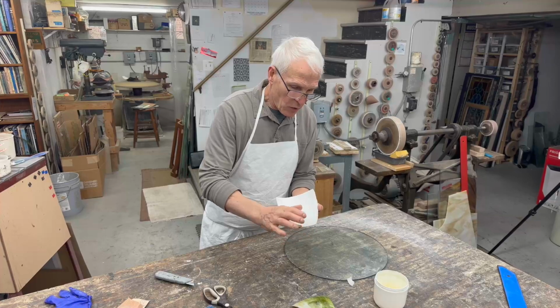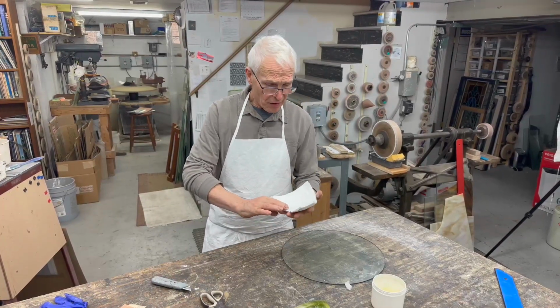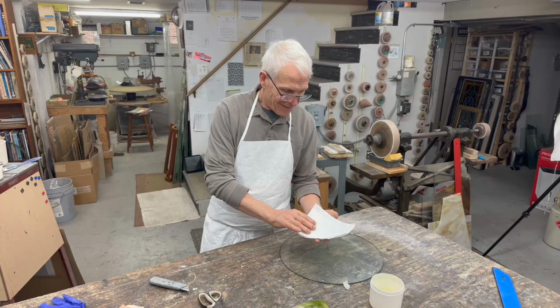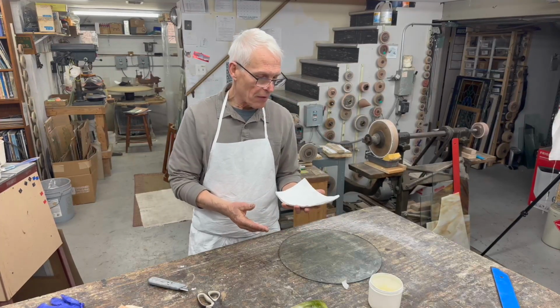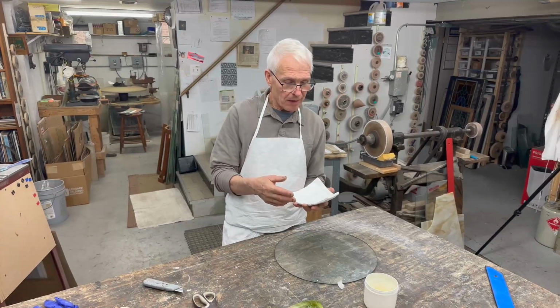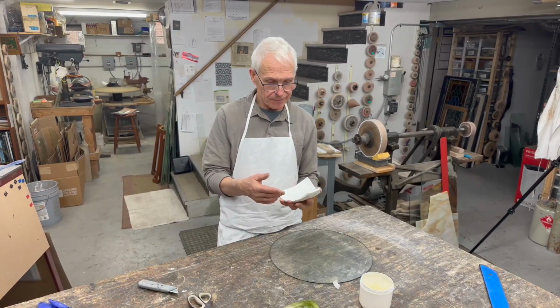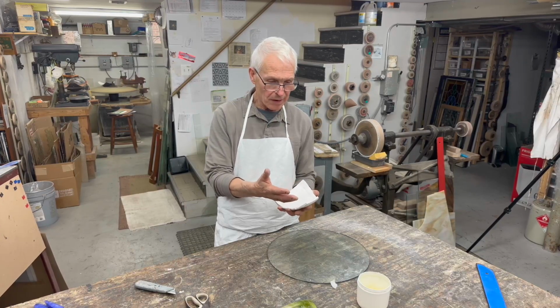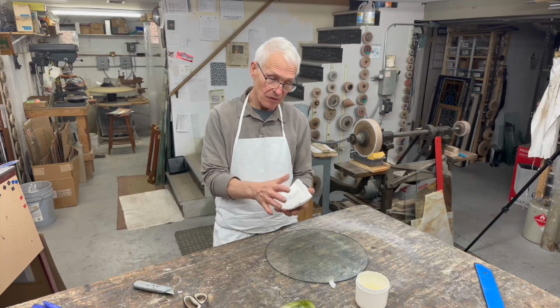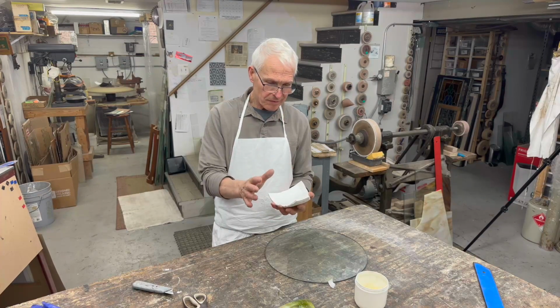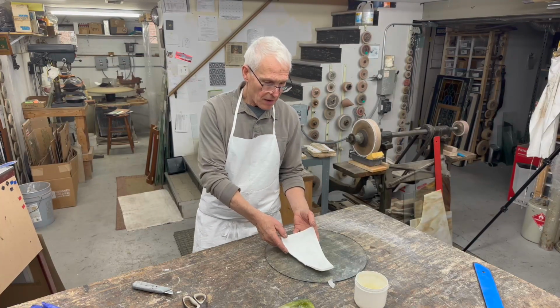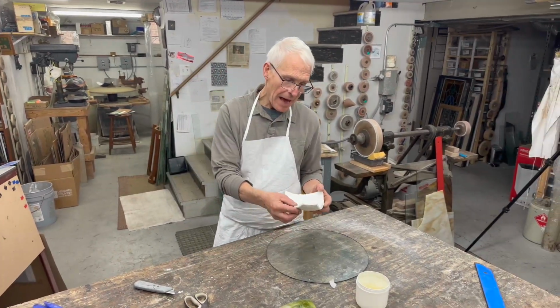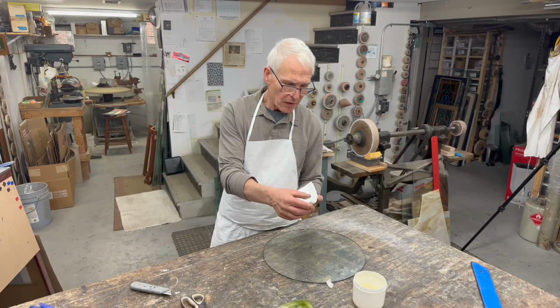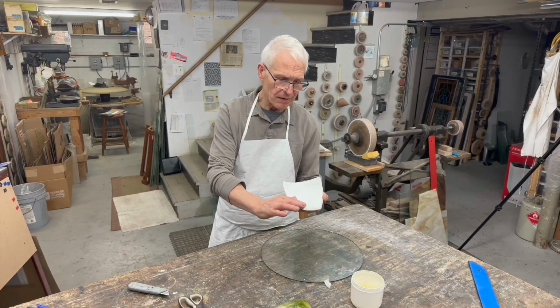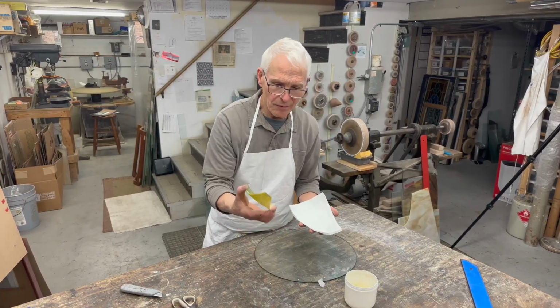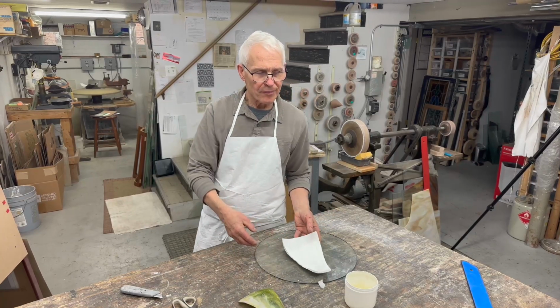So we've got our dry mold. We sanded the bulk of the ridge off, and there's two things you could do now. You could put another coat of the fiber hardener on and let that cure so it's a little harder, or you could just put the release on. If you were going to make a lot of these, I would suggest putting the hardener on after you sanded it. But if you're just going to make one or two of these replacements, you wouldn't have to go to that trouble.